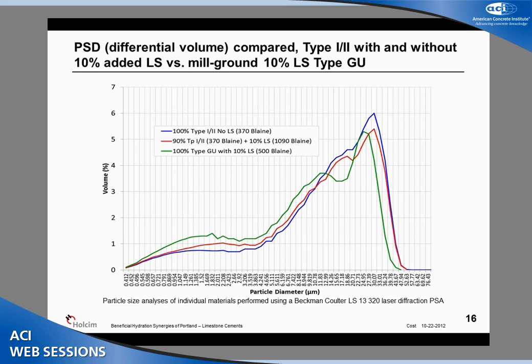The red is the resulting combination of 90% Portland cement and 10% ground limestone, and the green is the actual mill ground system at 500 square meters per kilogram. So you can see that we were indeed missing the concentration, I should say, of the very fine particles that are much more prevalent in the mill ground system.